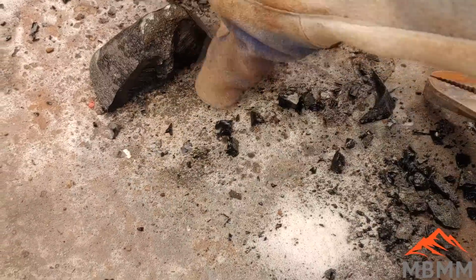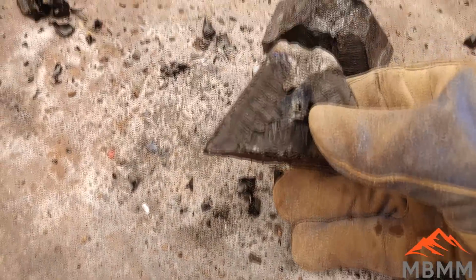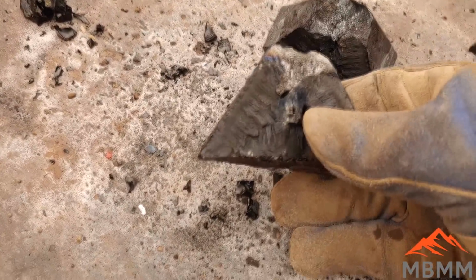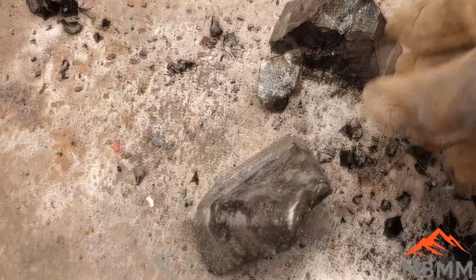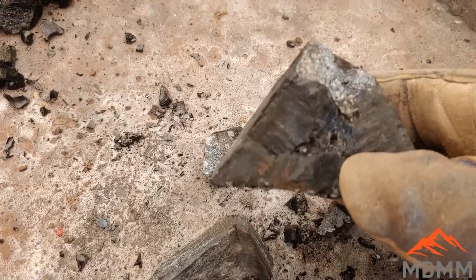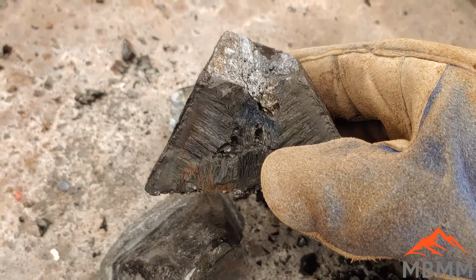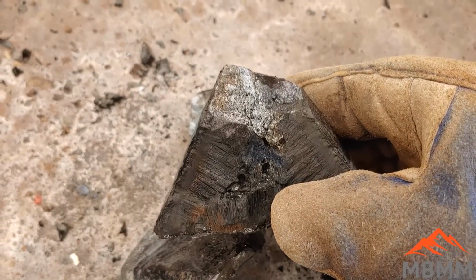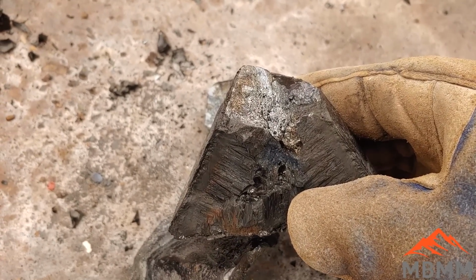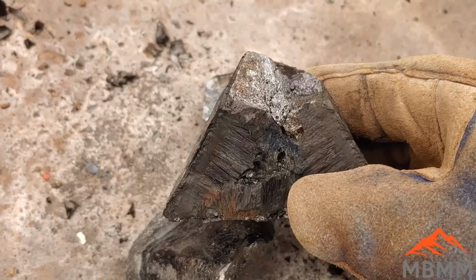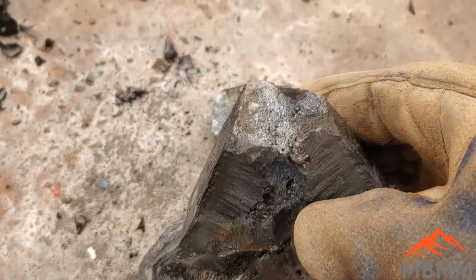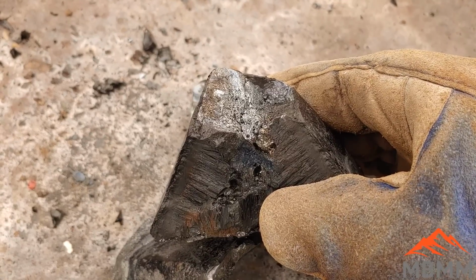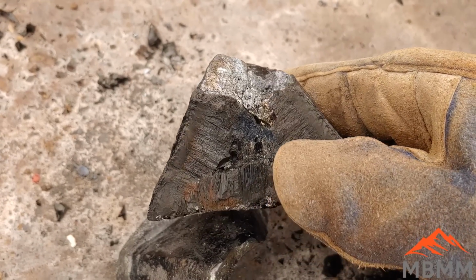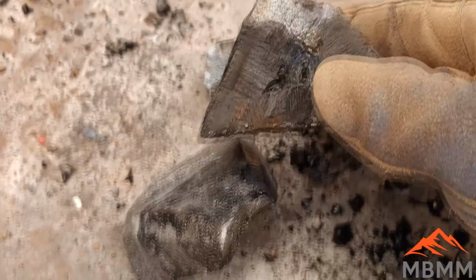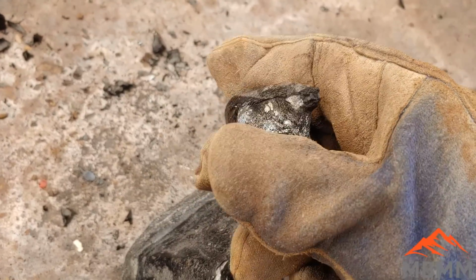All right, here's our matte. And look at there, we got a bunch of matte in there. And it even looks like, I don't know if it was too cold or what, but the matte kind of blurbed up into the slag there. It should be a nice flat surface interface between the slag and the matte. So that's pretty weird. And then here's our button.